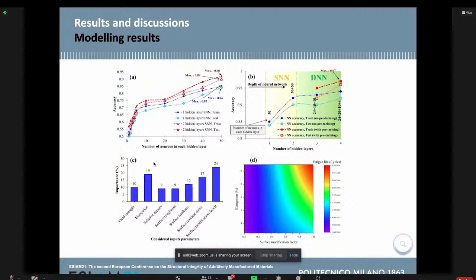After applying the neural network modeling and obtaining the best neural network architecture, we generate the model function with the best condition. You can see the best architecture of the network here. Then we applied a sensitivity analysis on the inputs to obtain the importance of each parameter on the fatigue life. It was found that surface modulation factor has the highest importance, and then elongation as a parameter of the material.